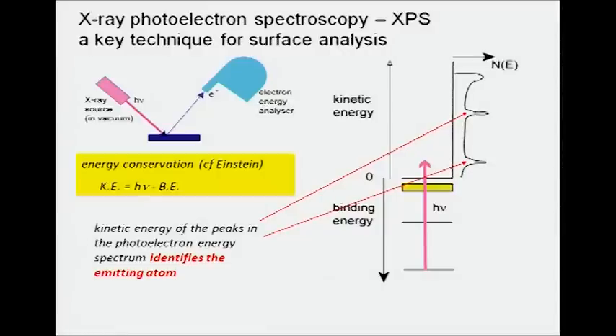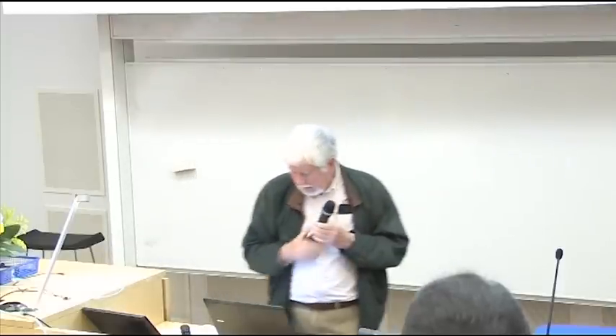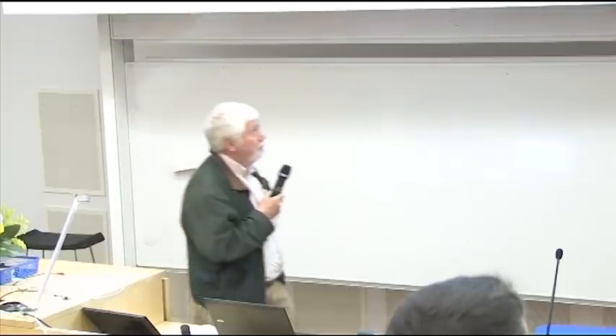photon, you kick out an electron from a core level, you look at the kinetic energy, from that you deduce the binding energy. In conventional XPS, a lot of XPS is done to determine just the composition of surfaces, and it relies on the fact that the core level binding energy is essentially characteristic of the atomic species. And it's a surface-sensitive technique, because in this energy range, the electrons that come out have a rather short inelastic scattering mean-free path.